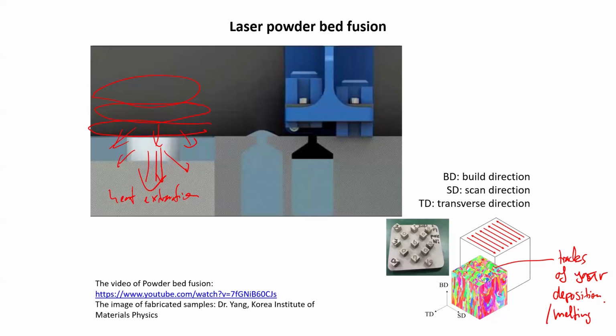And you will also see the outcome of the heat flow. And that gives you a very, very complex microstructure, also with a lot of defects because of the rapid shrinkage and rapid solidification. So you introduce a lot of strain because of shrinkage going through the liquid to solid transformation and due to the cooling. And that means you create strain, which can also introduce huge dislocation density. So the strain is actually large enough to go above the elastic limit into the plastic regime. And this is a highly defected structure which you get.